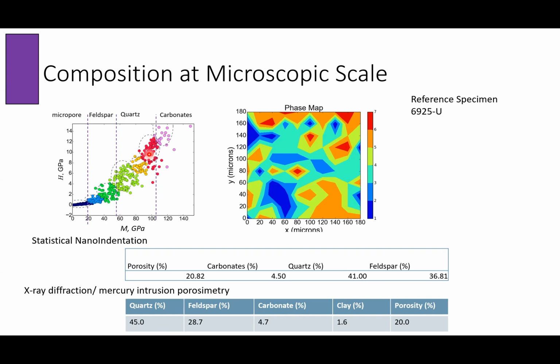Yeah, it's also on this kind of graph. It's about the nanoindentation data, because as you said, you have different phases. So you have the quartz, the feldspar, and each of them will have a different response. But then the nanoindentation could fall on a grain boundary or near a grain boundary. And near a grain boundary, the local stiffness and the local mechanical properties will be very different than in the center of the grain. I was wondering if this kind of effect is discussed among the people who study